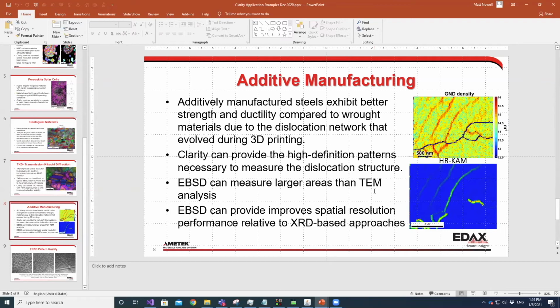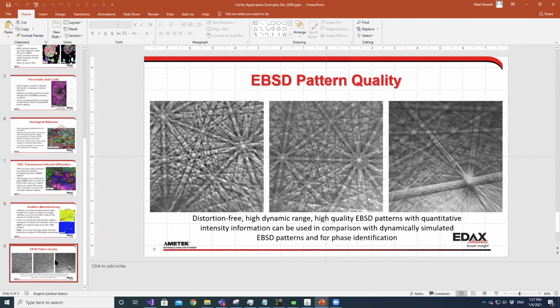And we can resolve out, say, where the geometrically necessary dislocations are present. So in this map here on the top right, we can see the dislocation structure. And we've compared things like this to TEM images, and we can see how the cell structures compare favorably between those. And then in addition to that, we can get really nice high quality patterns. This is from a range of materials.